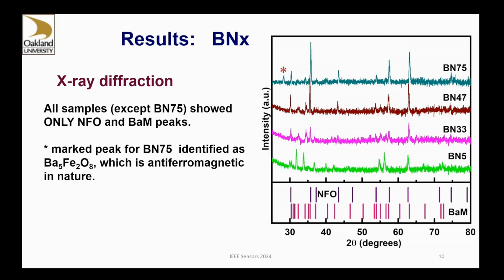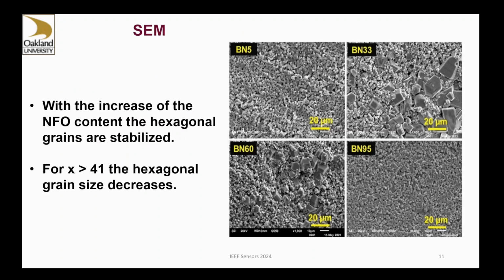And these are the X-ray diffraction data for the composites. As you see here, we don't see any impurity phases except at very high nickel ferrite or nickel zinc ferrite composition. This is the impurity phase which we identified as antiferromagnetic in nature, so it will not affect the ferromagnetic phase in any true sense.